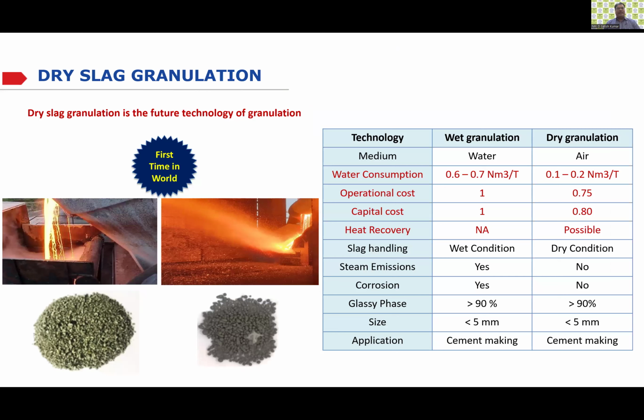Recently, we are also developing a technology for this granulation process, which used to happen with water, which was one of the reasons for the highly porous material. We developed a technology for dry granulation of these materials. Now, by doing dry granulation, I'm getting a more rigid structure, and these fine aggregates are more rounded directly and more useful, and a lot of processing steps can be avoided. So this is also a development from the iron and steel industry to convert these wastes into products which can be sustainably utilized in other industries. So dry granulation is a future technology which is coming for iron and steel making people, especially for granulating this blast furnace slag.